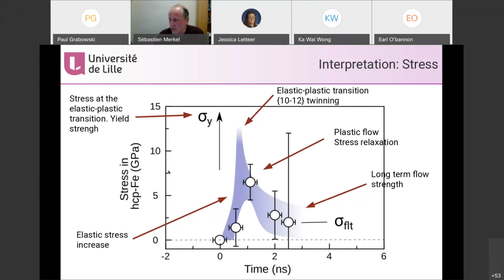And our values of stress are not so high. The peak stress we didn't measure, unfortunately. We didn't know this was going to happen. But it's probably quite high. Actually it's quite surprising that we get very low stress values, on the order of 2 to 5 GPa, later in the compression. There are predictions that the stress curve should behave that way.